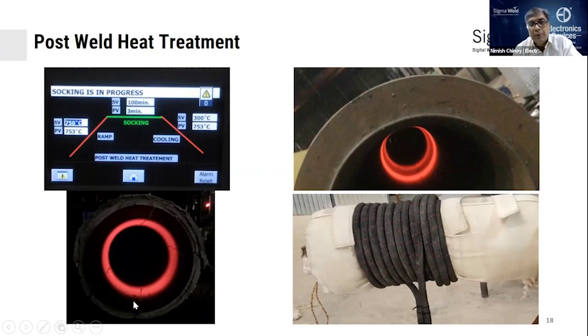These are 4 thermocouples giving feedback, and you can see this is the ramp rate you can preset. Right now it is in soaking period for about 100 minutes. 3 minutes have passed. The actual temperature is 753. Once the soaking, finishing, and cooling starts, it will reduce the temperature power slowly. So you have a gradual gradient up till you reach 300 degrees, and then you will let it naturally